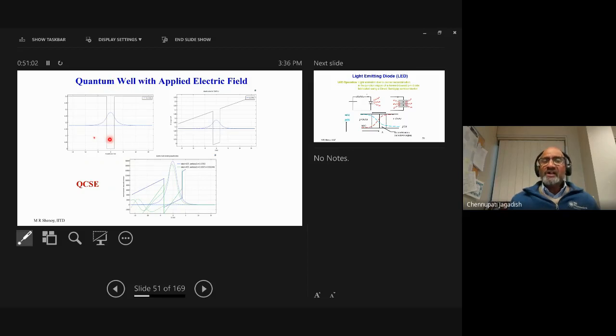There is something called the quantum confinement effect, and if you take a quantum well, you see the electron wave function here. In this case, I'm only showing the electron wave function, and the hole wave function will be in the other direction. Then if I apply an electric field, band bending takes place, and the electron wave function starts broadening and also shifting. That means the absorption wavelength can be changed quite significantly. Thereby this can be used for modulators, by applying an electric field.